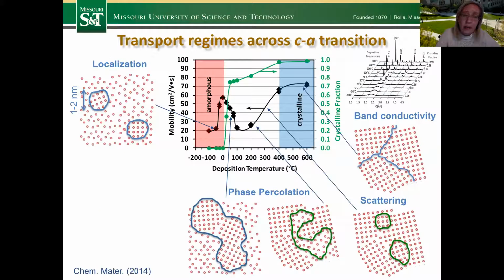And these are, again, measurements by my colleagues from Northwestern. So what we know for the indium oxide specifically is that as we lower the deposition temperature from 600 all the way down to very low temperatures for the deposition, we can go from the crystalline material to some phase percolation and then X-ray amorphous. So if you look at the X-ray, the peaks are gone, and we can calculate the crystalline fraction from there, which is also shown here in green. The peaks are gone. So in terms of the X-ray, we can call this material amorphous after 0 degrees Celsius.